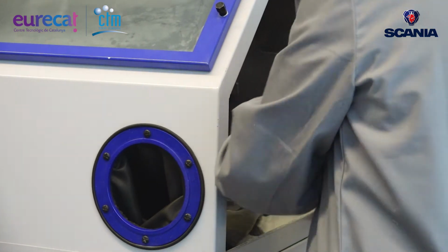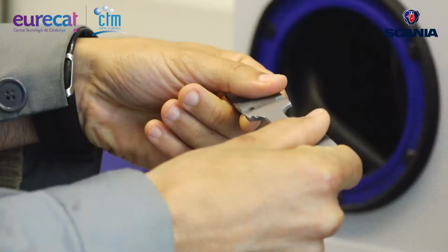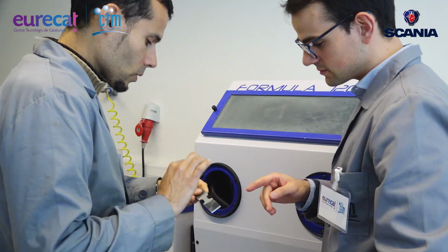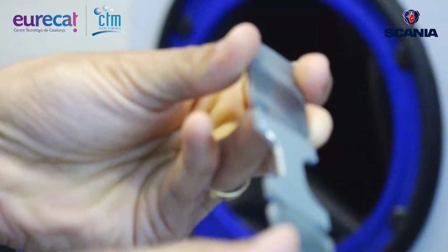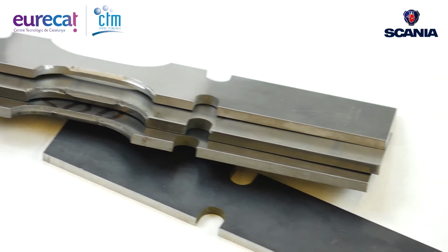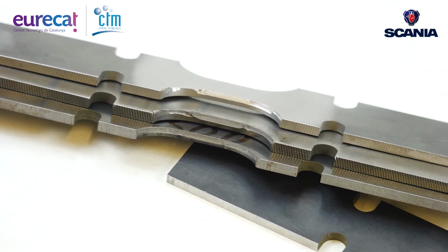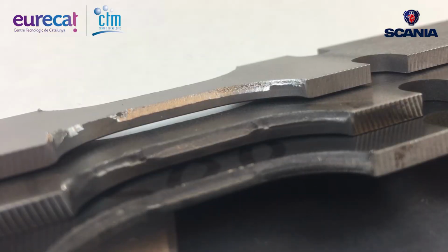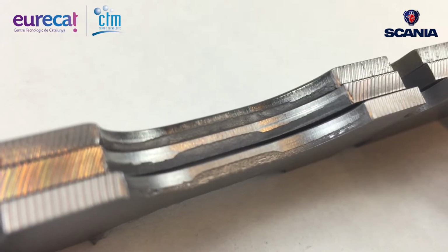The fatigue strength is also influenced by the material microstructure, because the finer the microstructure, the more cycles are needed to make the crack propagate. In our laboratories, we carefully prepared and tested the specimens of 3 steel grades at 4-point bending fatigue to evaluate how the combination of all of these parameters can affect the fatigue performance of high-strength steels.